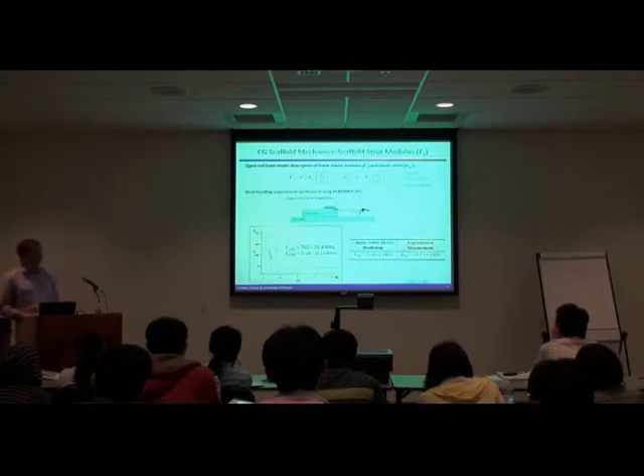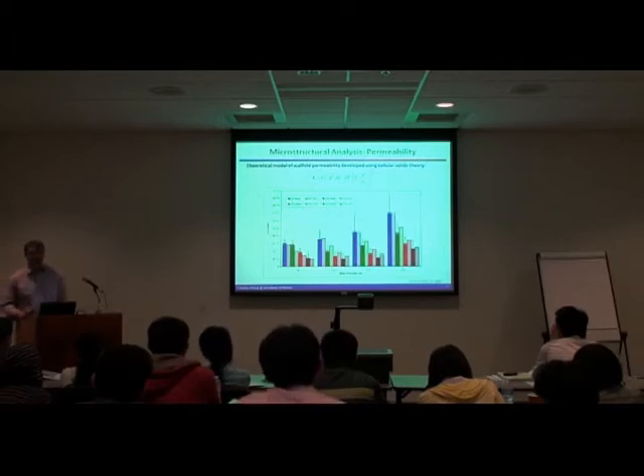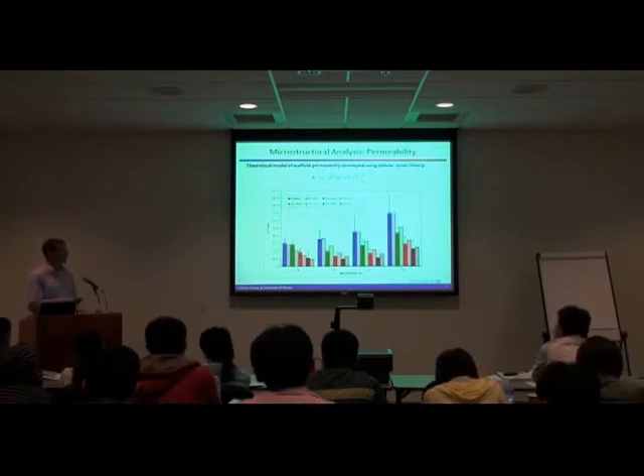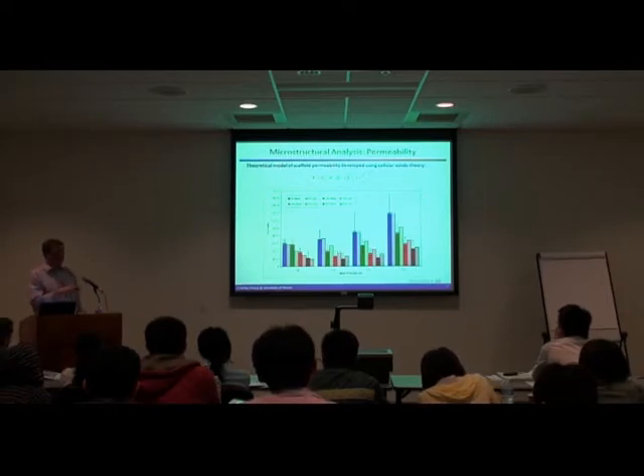And so this is starting to give us the basis, we think, to have a series of materials we can use for a number of quantitative measurements of biology. One last thing to give you a sense of is that cellular solids theory is not just useful for mechanics, although it's one of the more initial things we looked at. You can develop model theory to describe a number of physiological properties of a porous material. Another one that you as a tissue engineer might care about would be the permeability of your material, so the ability to get nutrients into your scaffold. I'm not going to go through the model formulation, but you can develop a relationship to describe the fluid mobility or permeability. It's just that there's a different constant out front, in terms of the pore size of the biomaterial, the applied strain on the biomaterial, so if you're loading in a bioreactor or putting it into the body, and the relative density of the scaffold you start out with.